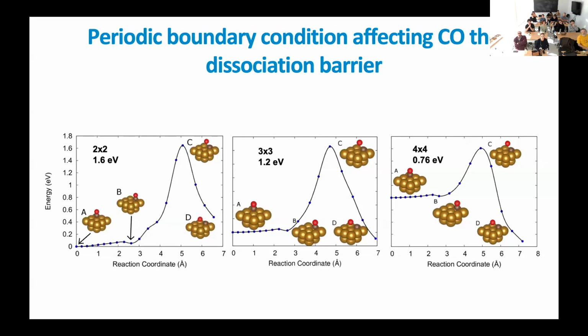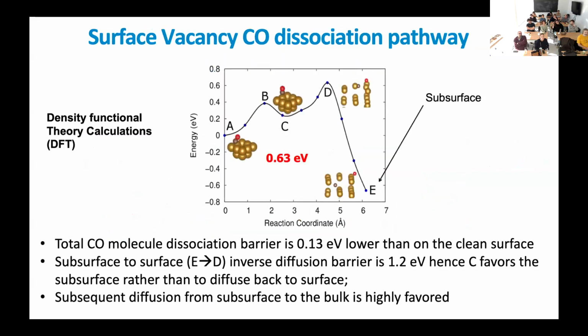So you see that if you engage in DFT calculations, there are so many things that you need to take into consideration to be able to get sensible results, okay? And having some hints from experiments helps you enormously. Okay? And in this case, in the vicinity of a vacancy, we had no choice but to consider the 4x4, because this is already too small for having a vacancy and the CO nearby.